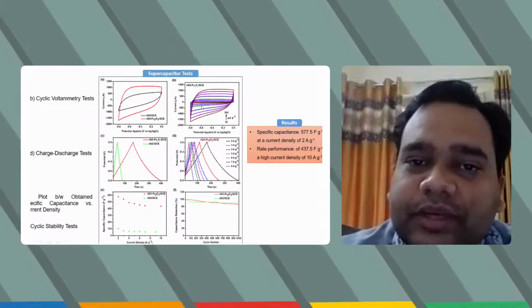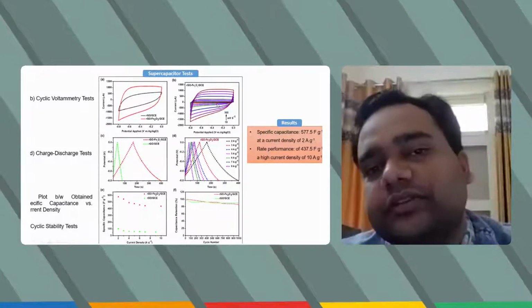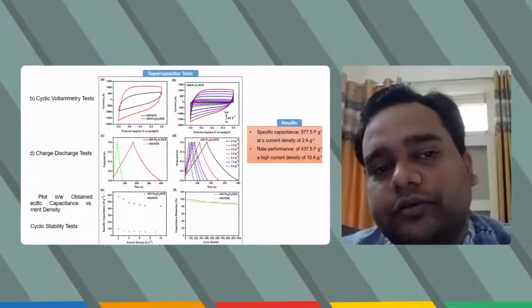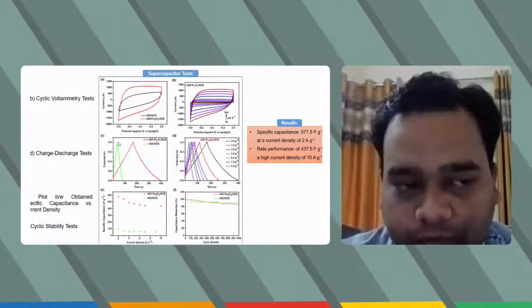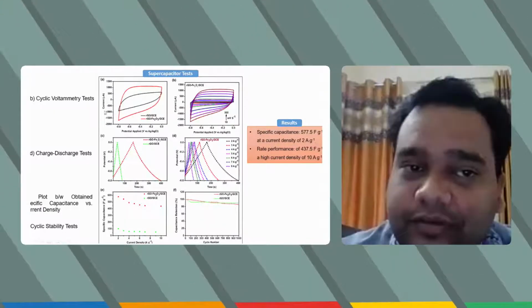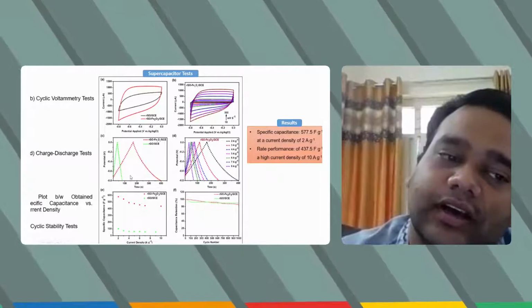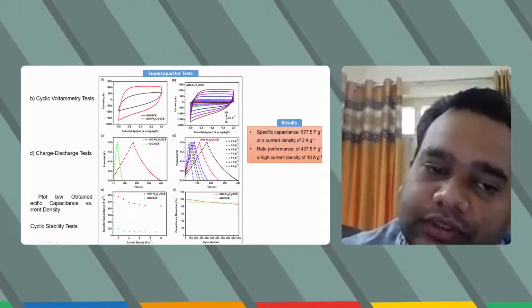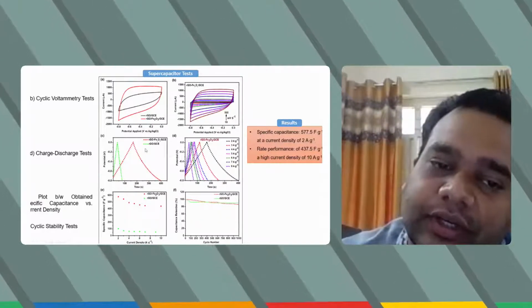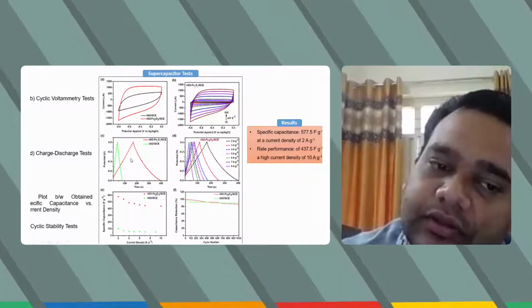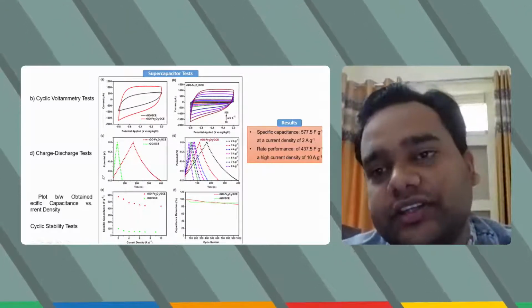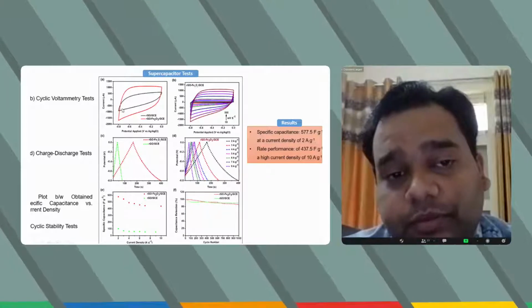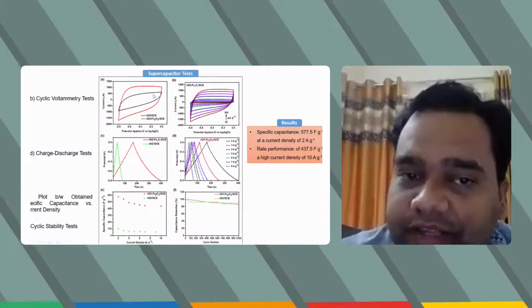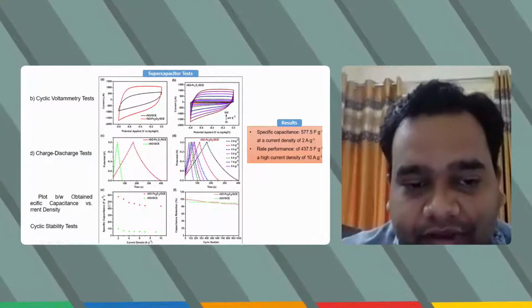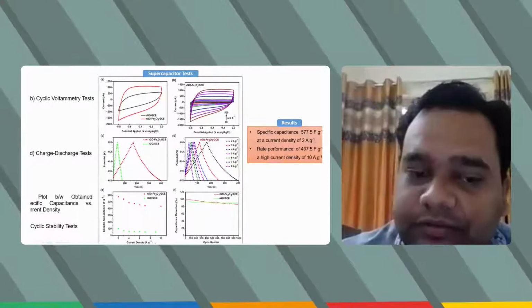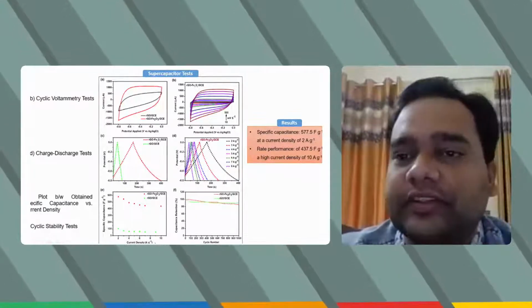And when we perform the same experiment at different scan rates, its shape is maintained. So we can say it is giving high rate performance. And similarly, we confirm this by the charge discharge test also. So this is charging and this is discharging. In case of the composite, you can see it exhibits high charging and discharging time. Based on this, we calculate the specific capacitance of the supercapacitors, and when we plot it with respect to current density, we apply current density and we obtain specific capacitance.